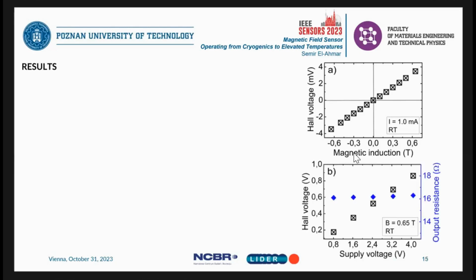Here, also the dependence of the signal of the sensor versus the supplied voltage of the sensor. And on the right side, this blue part of this graph shows you the output resistance of the sensor. So you can see that at higher supply, the sensor is still stable, which is very nice, because at higher supply, we can get also the higher base signal.